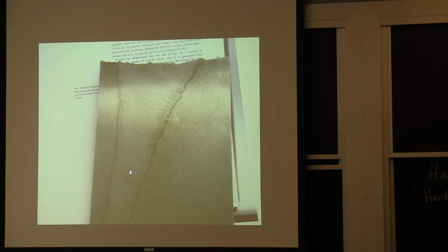This was actually their second or third attempt. The first attempt cracked before they ever got it on a crane to put it back up. The second time, they did a better job of preheating to get rid of the hydrogen and post-heating, and they got it up onto the press. And the first time they hit it for a forging, it cracked again, because they didn't really get rid of the hydrogen, and when you have something this thick, you bury